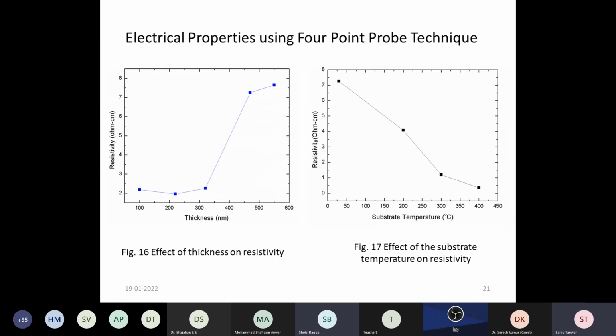Then the same can be correlated using the 4-point probe technique, resistivity measurement. We can see the resistivity is almost constant, but it suddenly increases for the 470 nanometer film, because of the high number of pores. And similarly, as we increase the substrate temperature, the resistivity sharply decreases because refractive index and density are increasing, so grains are closely connected to each other, and their resistivity will be low.